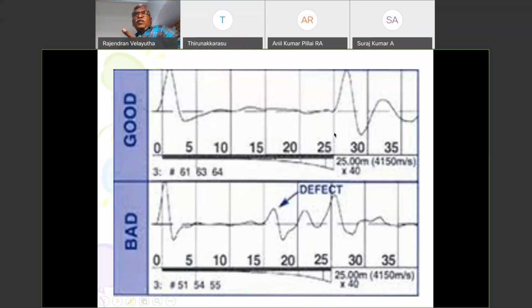For some reason, if the concrete does not have that amount of velocity, then obviously your pile length calculation will be wrong. So what we need to do is, better to take a core from that pile, check what the actual velocity of the concrete is, take that output as an input to be given in your pile integrity test, and then you'll be able to get the right depth of the pile. So what I'm trying to say is that with one single test, let us not try to conclude. It should be a combination of 1 or 2 tests, and also with our best engineering judgment, and then we go for it.